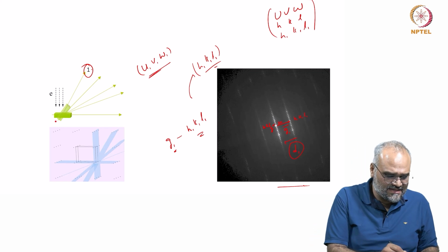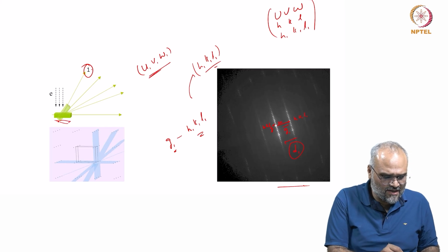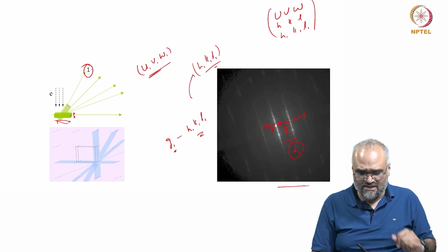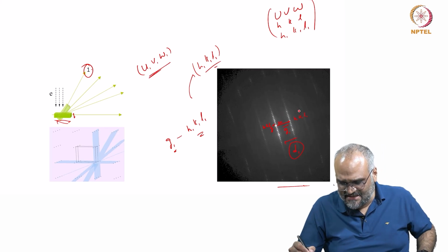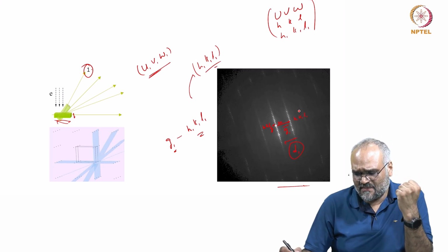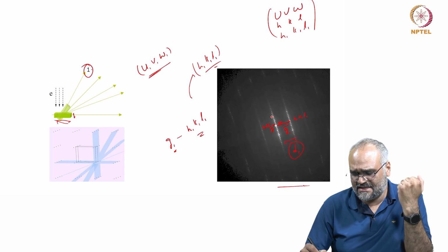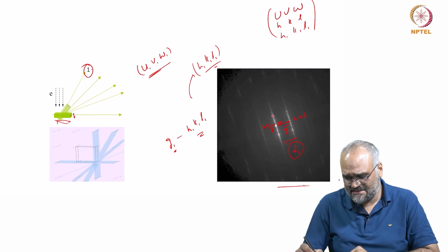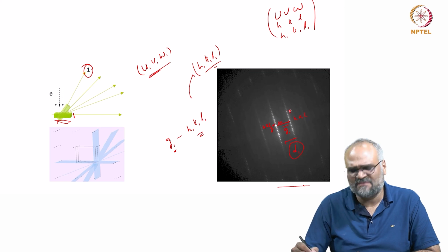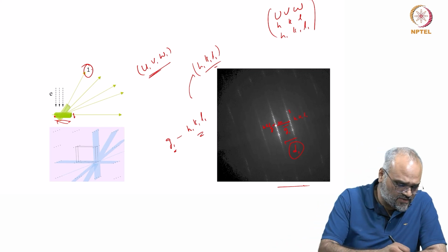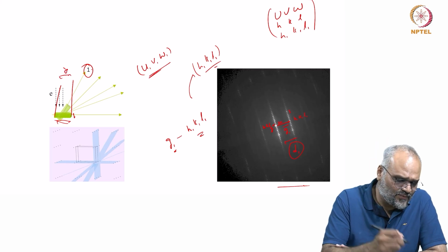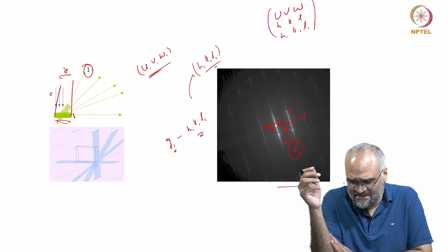Please note that I have intentionally given you a crystal with an elongated axis here and a smaller axis here. So, why do I do this? If you look at these reflections here, when we say that the electron diffraction pattern is actually the reciprocal lattice, and what you see here is inversely proportional to the real space, the value D that I get from two subsequent reflections would correspond to a plane with a very large D spacing in real space.